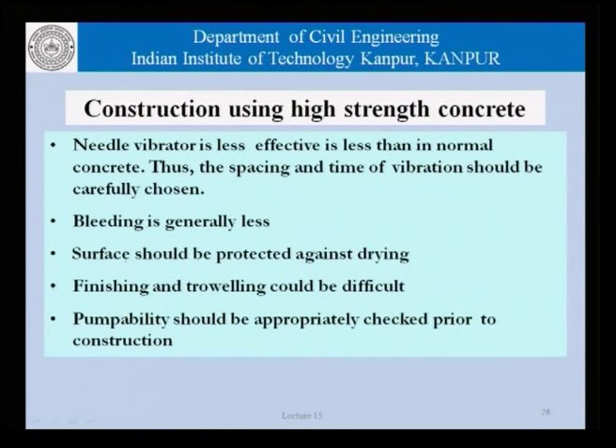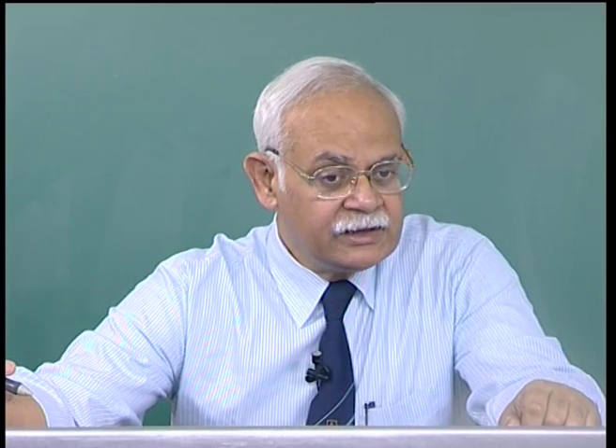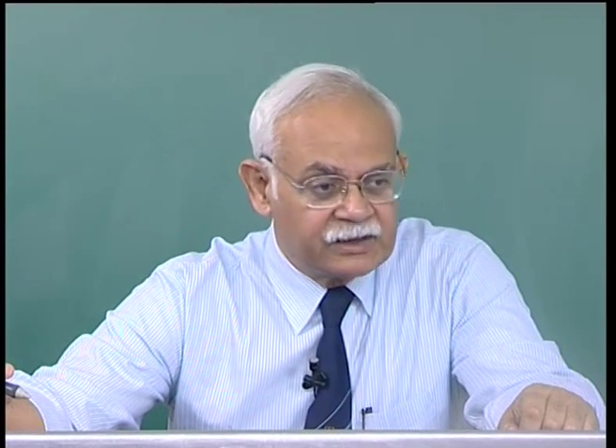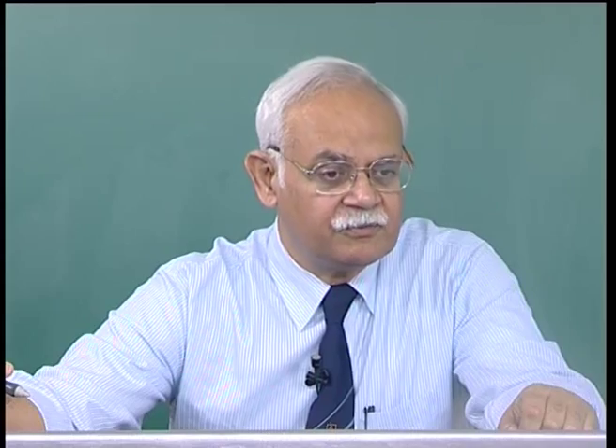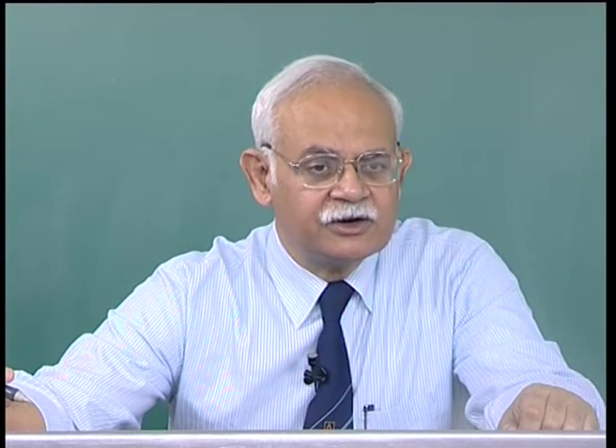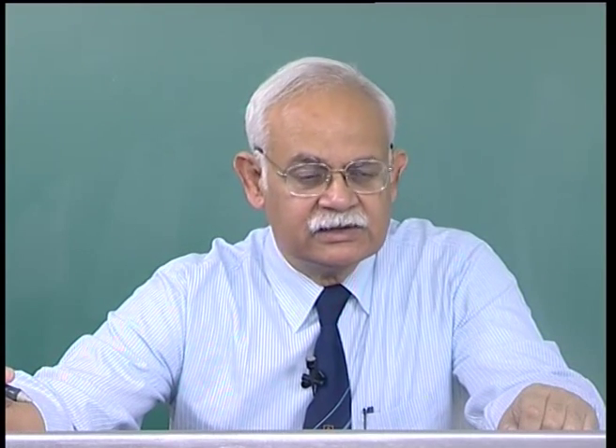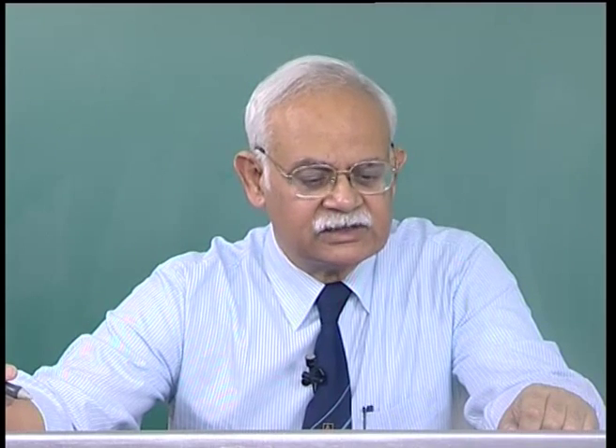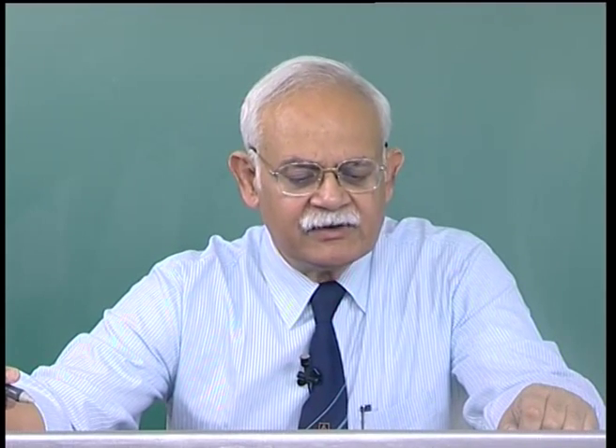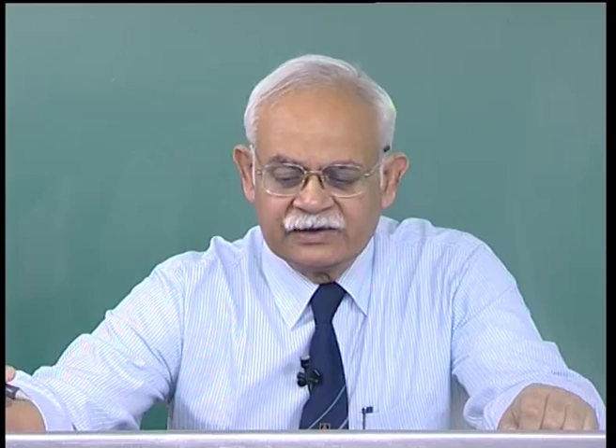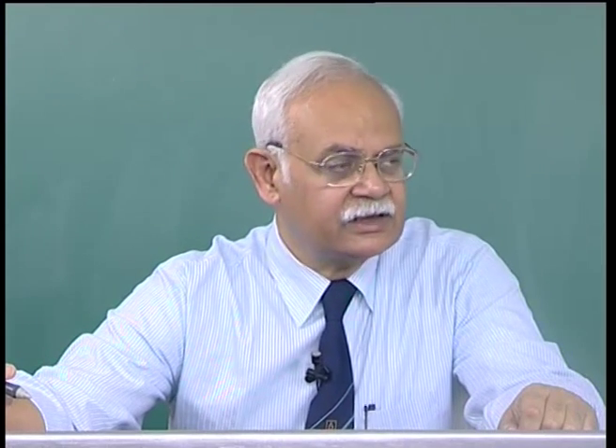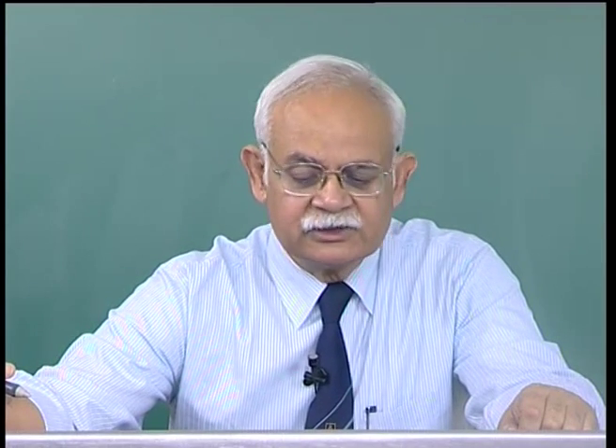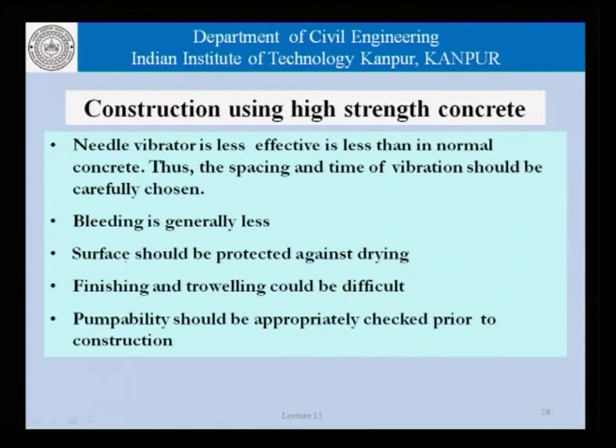When it comes to construction using high strength concrete, we must remember that the concrete is now characterized by the presence of a large amount of paste or a large amount of mortar, which makes the concrete very viscous. And once the concrete has become viscous, then needle vibrators are less effective than in the case of normal concrete, and therefore, the spacing and the time of vibration needs to be carefully chosen.